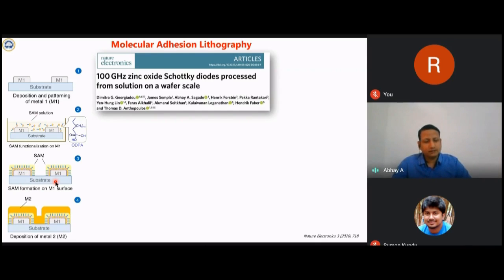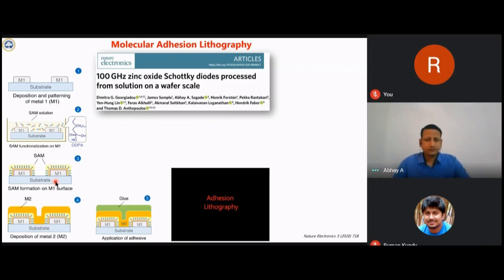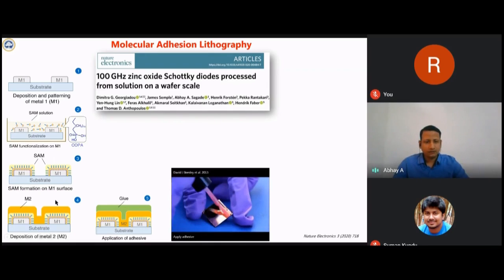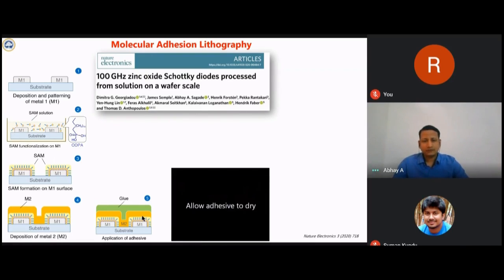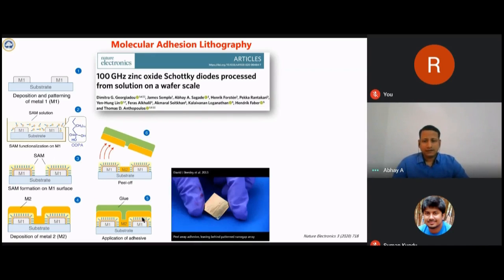In the next step, you deposit your metal 2 everywhere on the substrate. I will show you here one small video to show the next step. In the next step, apply a glue. This is now your chip on which you are applying a glue, and let it dry for some time. Then take your tweezer and just peel off that top layer of metal 2. You can see you end up with a substrate with metal 1, then the SAM molecule, and metal 2 left in between the two metal 1 layers.